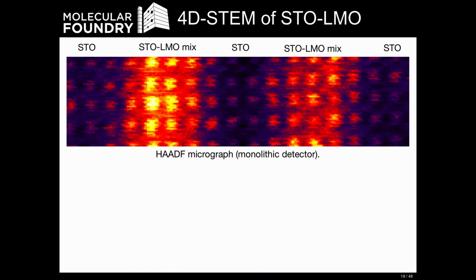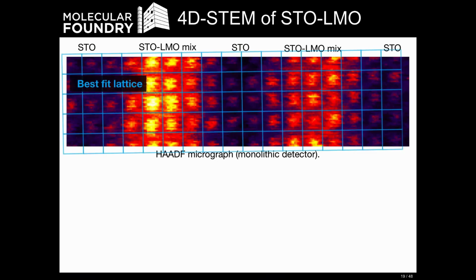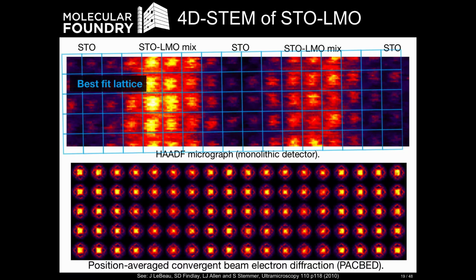To do that, we're going to turn to the PACBED technique. This was introduced by LeBeau and Stemmer, Les Allen, and a few other people. In the 4D-STEM sense, we're going to fit a mean lattice, a best fit lattice, to all of our atomic sites. Under each unit cell, I'm going to take all of these pixels and average them in the diffraction plane to form a PACBED pattern, a position averaged CBED pattern. So for each unit cell, we produce a very clean, high signal to noise diffraction pattern.